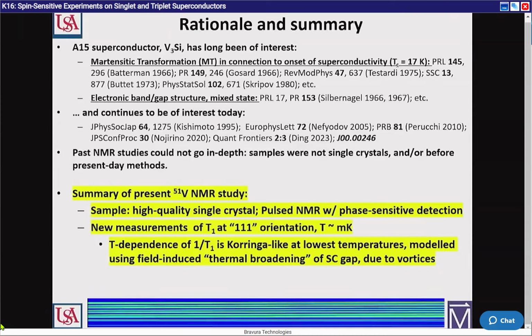Our contribution is, number one, pulsed NMR with phase-sensitive detection. Number two, a really awesome single crystal sample. And what we're going to show you today are T1 measurements in the 111 direction down to millikelvin temperatures. We believe this is very new. And what we're going to see, spoiler alert, is that we're going to see